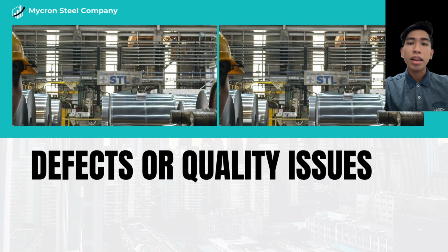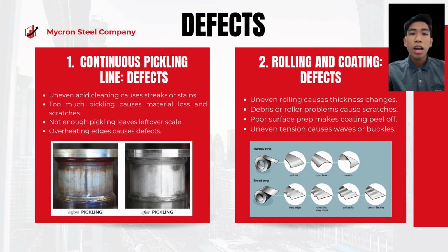Next, I will be discussing defects or quality issues that occur during various stages of the metal processing line. These defects can significantly impact the final product quality and must be carefully controlled. Starting with the continuous pickling line, uneven acid cleaning can leave streaks or stains on the metal surface, affecting how it looks and works. Too much pickling removes too much material and causes scratches, making the metal weaker. Not enough pickling leaves behind unwanted residue that affects the next process. Also, if the edge gets too hot, it can create defects that make the metal less strong.